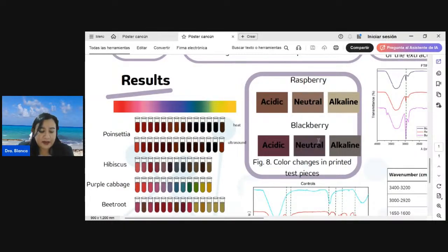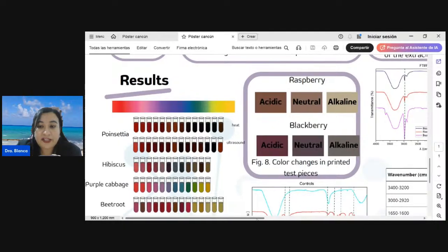This was after incorporation into the PCL matrix and subsequent printing. The produced specimens retain part of this chromatic functionality. The printed structures exhibit visible color difference, demonstrating that anthocyanins can remain active after processing. These findings support the possibility of developing smart printed materials capable of signaling environmental food quality change through this color variation.